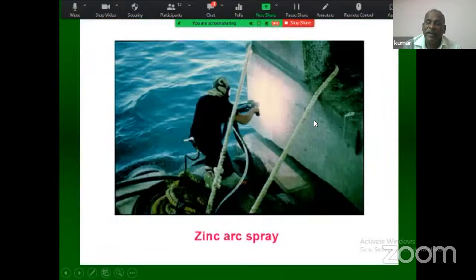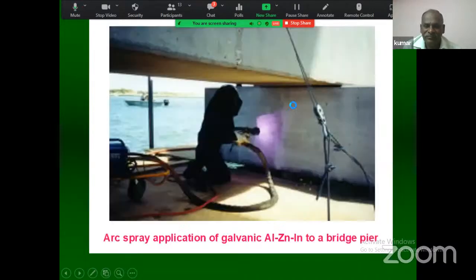There are sprays also which one can do. On the surface of the concrete, you can apply a metallic spray, either zinc or magnesium or aluminium, anything you can spray on the surface. And through that, you can connect to the reinforcement. By sacrificial action, this metallic surface coating will sacrifice and your steel is getting protected. You see here again, this is the metallic spray.